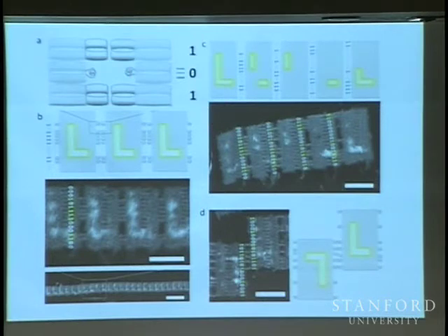Here we constructed a code with the following property. If the binary sequence of these edges lines up, it either matches at all 7 places where these little rigid cylinders are, and that's strong enough at this temperature for them to stick together. Or for any possible translation, it only matches at 4, and 4 is too weak under these conditions for these things to hold together very well.